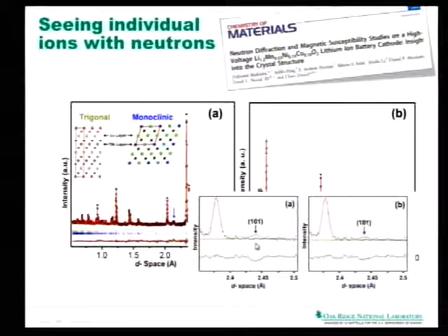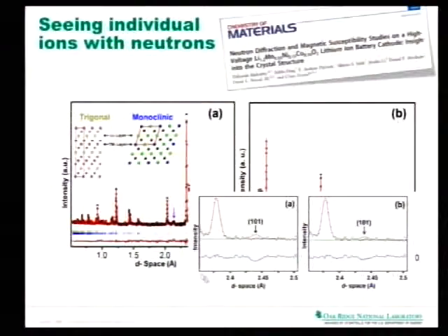You take some lithium ions, you take them out of the lithium layer, you put them into the nickel layer, and you take some nickel ions and you put them into your lithium layer. You start fiddling around with that, and Debashish Mohanty spends hours and hours on doing that by hand. So you're taking your crystal structure, you exchange some ions, you calculate all of your pattern again, you try to see if it fits.